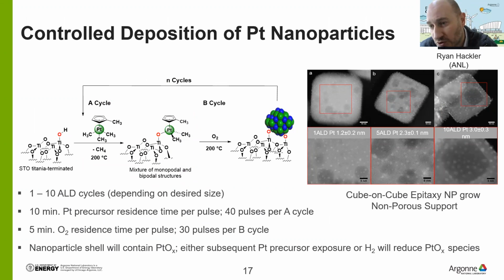As I mentioned before, we want to use atomic layer deposition, because depending on the number of cycles of the platinum deposition, we can control the particle size. These are 3 examples. We can really fine-tune the particle size based on the properties that we want to achieve the particular carbon-carbon bond cleavage. 1 atomic layer deposition cycle gives roughly 1 nanometer, 5 cycles 2 nanometer, 10 cycles 3 nanometer, and so on. We really have these nice knobs to control the particle size. And why is that particle size important? Because we can control, for example, the ratio between edges, corners, and terraces. And we know that these different sites on nanoparticles have different activity.